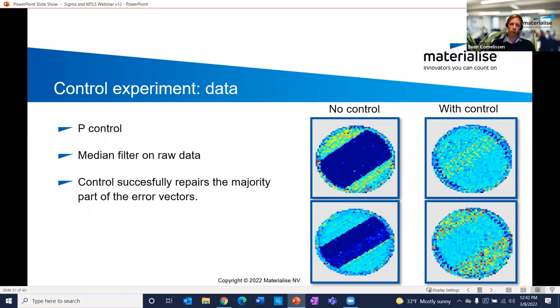And so on the left, you see two slices of the reference experiment, which I just showed you the CT scan and the data. On the right, you see the Sigma Labs data from exactly the same experiment, but with closed loop control enabled. And so what this data at least suggests is that for the majority of the vectors, the errors are controlled out.